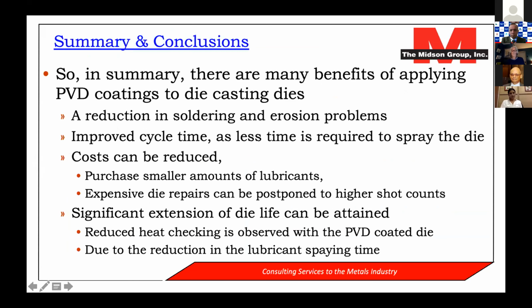So, in summary, it appears that there are many benefits of applying PVD coatings to die casting dies, not just in terms of small cores or small inserts, but larger portions of the die, or maybe, as we did here, the entire die. Firstly, a reduction in soldering and erosion problems. That's been known for a long time that PVD coatings provide those kind of benefits. But apparently you can get an improved cycle time as less time is required to spray the die. Cost can also be reduced. You're purchasing smaller amounts of lubricants, and expensive die repairs can be postponed to higher shot counts.